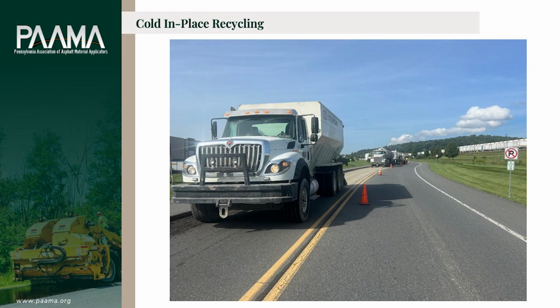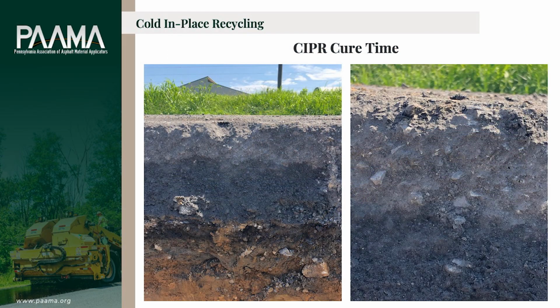They're in close proximity, giving the public less chance of driving into that material. And as I talked about earlier, I talked about the cure. Well, here's a site. We cut this out purposely. So within the first day, that top 2 inches of a recycled base has cured out. But it's that bottom 3 inches that we need to get the moisture out of. We need to get that dried out, and that's why we use the Portland cement. It drives that moisture out within 3 days.